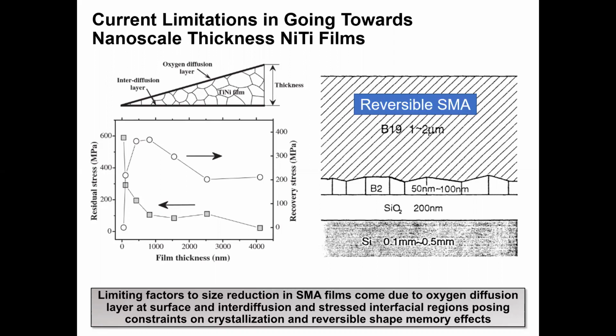So the residual stress also takes on very large values in this nanoscale thickness range, and this highlights the interfacial regions with much higher residual stress due to the CTE mismatch between NiTi and silicon substrate, and then the high crystallization or annealing temperatures required to shape set the SMA in the first place. So each of these constraints shown here, as I said, impose limitations on the volume of material available to participate in the reversible phase change.